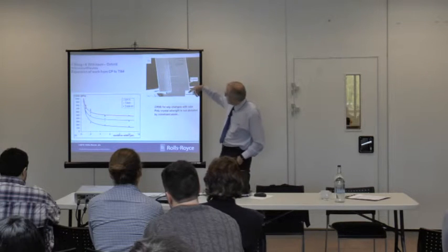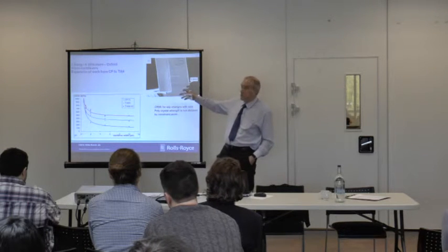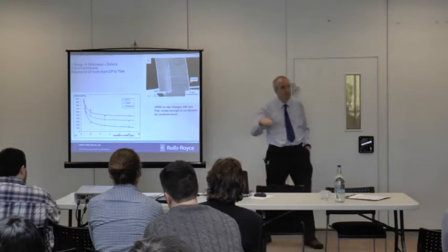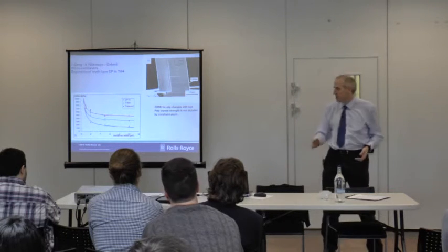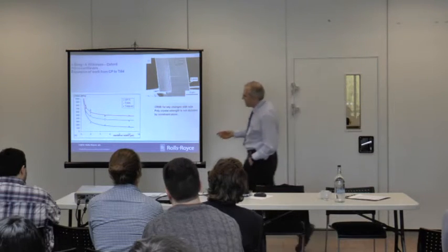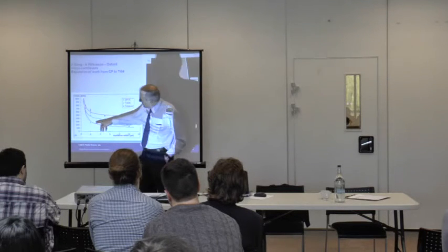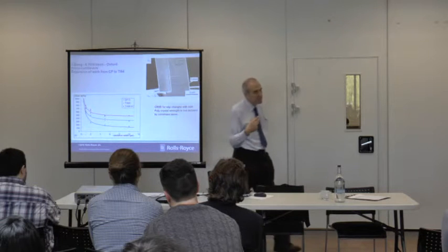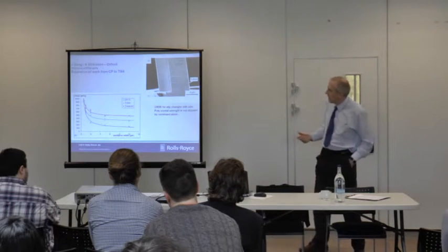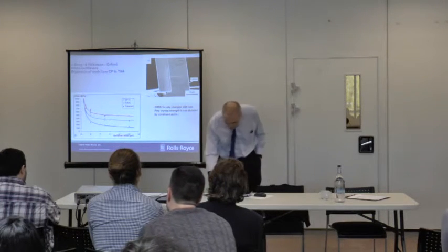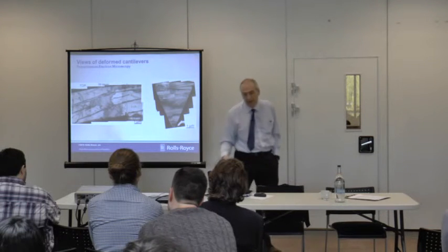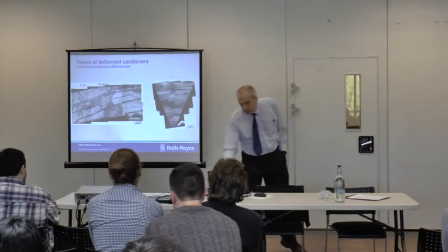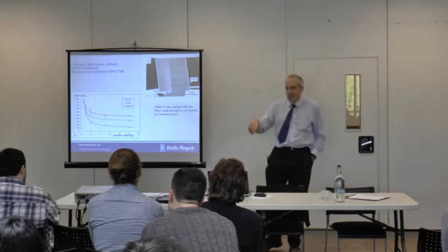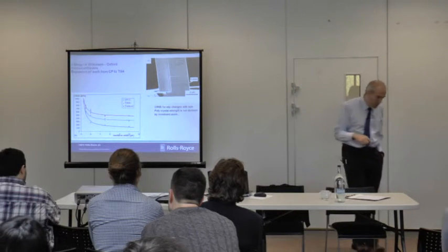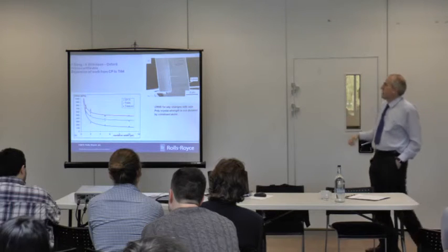You can take these things down to less than a micron across, and you can bend them, twist them and press them, and you can get data out. So in titanium alloys there, we can say, oh look, once we get down below 2 microns, that's where we're starting to get into strength, and we can decouple chemistry and length scale effects in that. So that's quite cool. Some neat experimental kit drives that. They're triangular shaped things. If you imagine a cross between a diving board and a Toblerone, and you load the end.